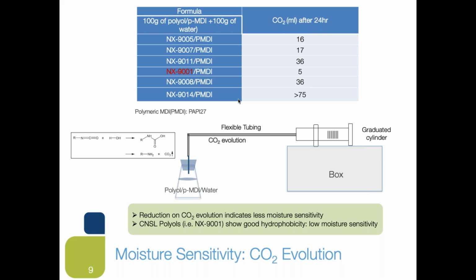This study is to explain the moisture sensitivity nature of, in general, polyurethane technology. One of the ingredients that can react with moisture is the isocyanate. As you know, when isocyanate sees moisture, water, it can turn ultimately to an amine functional group, and at the same time emits CO2 gas. And as you can imagine, CO2 gas can create defects in your coatings and adhesives. Ultimately, the durability of your polyurethane system will be impacted. So from this study, a higher amount of CO2 means your system has a greater moisture sensitivity.